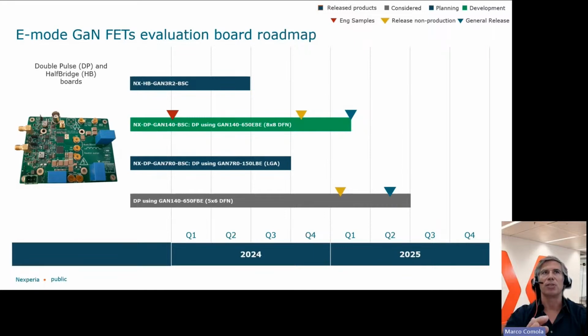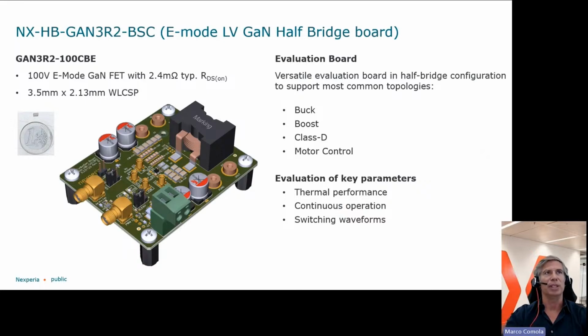But I want to focus your attention on the first one, the board NX HB GaN 3R2 BSC. It means Nexperia half bridge GaN 3R2, the 3.2 milliohm 100 volt device, with bottom-side cooling package. To give an idea of the device, you can see on the left side the size of the package, this chip scale package versus one euro coin. The size of the device is 3.5 millimeters by close to 2 millimeters. This 100 volt E-Mode GaN FET has 3.2 milliohm maximum on-state resistance, and 2.4 milliohm is the typical value. And the evaluation board that we did in Nexperia uses two devices, of course, using the GaN FET.